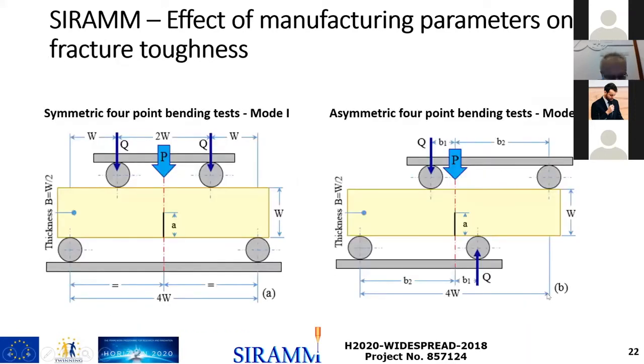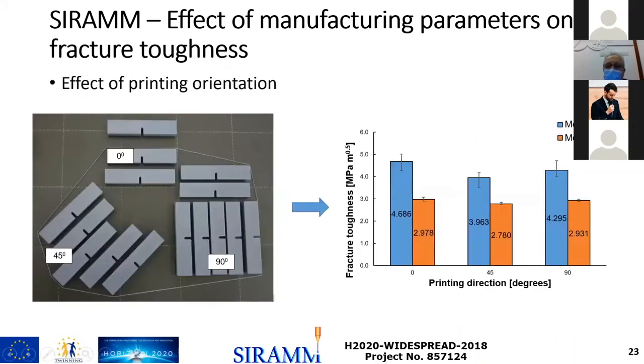For the fracture toughness test, we determine mode 1 and mode 2 fracture toughness using single edge notch bend specimens loaded symmetrically in 4-point bending for mode 1 and asymmetric 4-point bending for mode 2. Also, we look at the specimen orientation. You can see here the specimens coming from the printer and the fracture toughness values. All the mode 1 fracture toughness values are higher than the mode 2. As numbers, for mode 2 fracture toughness, we have 2.78, the lowest obtained for the 45-degree direction, and the highest fracture toughness for mode 1 is 4.68, obtained for 0-degree orientation.